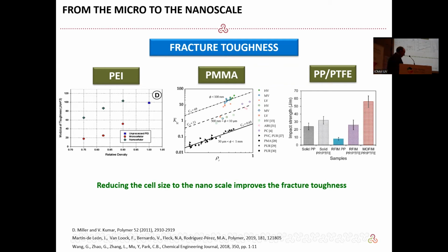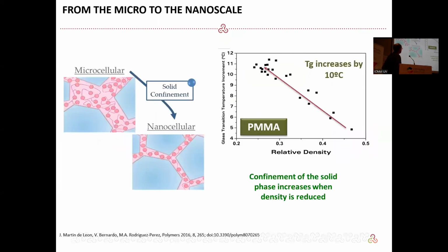Well, understanding this is not so simple because you need to go into the deformation mechanisms, the molecular structure of your polymer, and so on. It's not so easy, but we are working on that. But basically our hypothesis to explain this is what we call confinement. When we have the microcellular material, we have a different organization of the molecules at the nanoscale than when we have the nanocellular material. In fact, and related to the previous one, we have seen that the glass transition temperature of the polymer, in this case PMMA, increases significantly when we make nanocellular polymers.